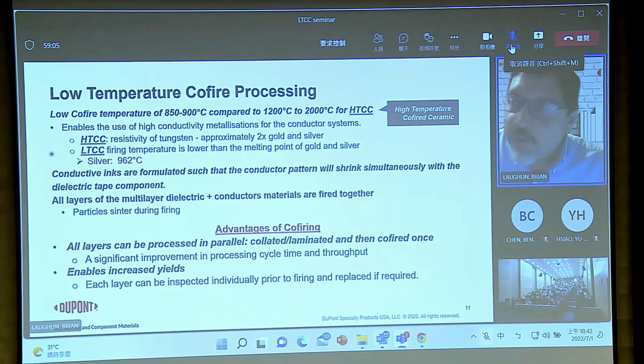But because you can do this co-firing step, not only do you make a 3D construction, but you save time on what's the more lengthy process of firing, which can be most of a shift or over multiple shifts to fire very large parts. And so the co-firing actually makes quite a big step for making this an economical process. You can batch fire lots of things at the same time. You're co-firing multiple prints at the same time. And so that's a critical economic step of co-firing.